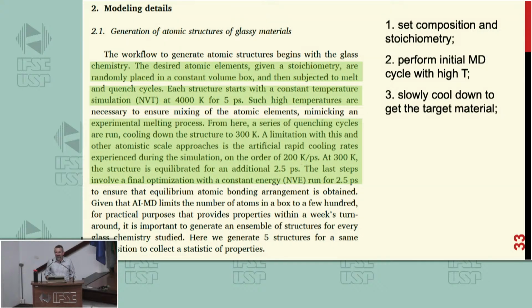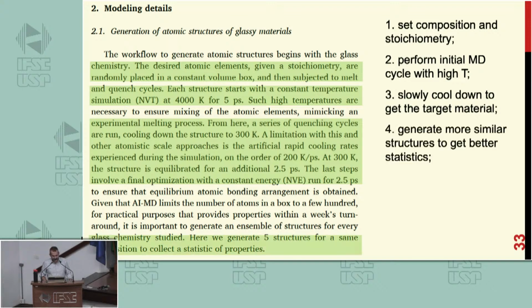So, okay, it's hugely fast, okay? But this shows that we are talking about different time scales in simulations and in experiment. And this is a big challenge that, as Zanotto said this morning, even the supercomputers that we have today cannot deal with this very well, okay? And at the end, they say that they do this procedure for many different glass structures. You take a stoichiometry, and they generate 5 different structures to get good statistics, okay? So that's what people do, okay?